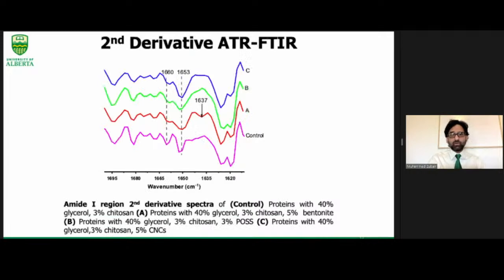Further, the second derivative of ATR FTIR was drawn of the developed protein films, and we can see that the peak at 1660 wave number belongs to the 3-10 helix, and the next peak that is around 1653 belongs to the alpha helix, while the one extra peak that we can observe in case of bentonite films around 1637 belongs to the beta sheets. And also these new types of interaction in case of bentonite might be the reason for the maximum tensile strength in case of bentonite-derived films.